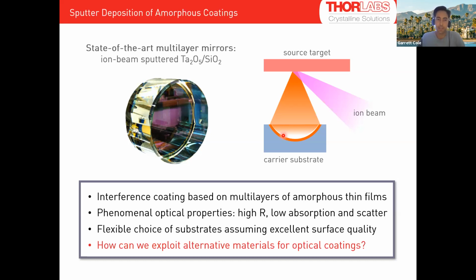But there are some disadvantages. These materials don't tend to operate at long wavelengths, so you're going to have a cutoff at maybe 3 microns or so. Thermal conductivity is relatively poor, at the level of 1 watt per meter Kelvin. And as I mentioned, they have high elastic losses. This will hopefully be the new physics you learn today, which is the Brownian noise topic. It's very niche, but something very interesting. These glassy materials tend to show very high elastic losses, that is, the imaginary component of the Young's modulus, which I'll go into in more detail later on. This tends to be high in these materials.